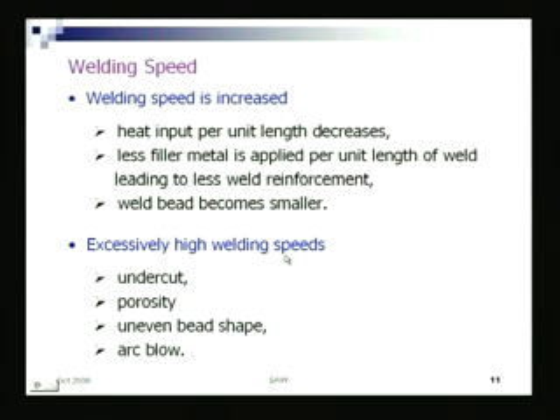Well, if the speed is now excessively increased, because I want more productivity, what will happen? It will lead to undercut, porosity, uneven bead shape, and arc blow. Why porosity? Because the gases will not be able to come out, there will not be enough time, before that the metal will freeze.